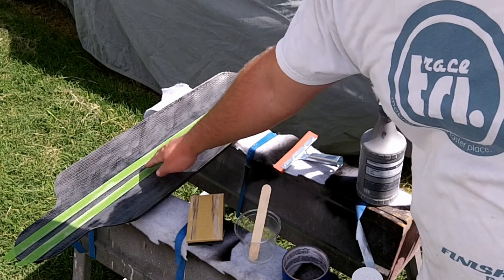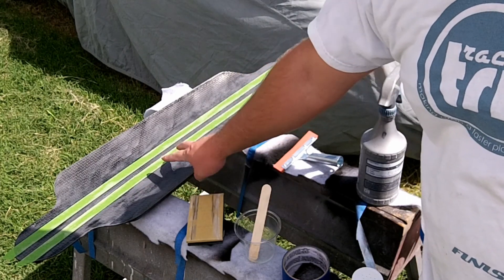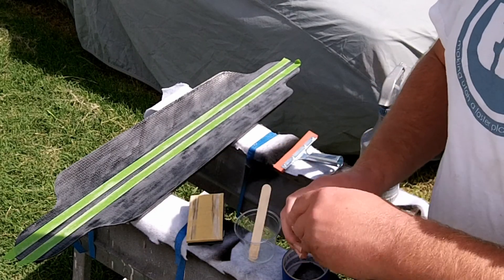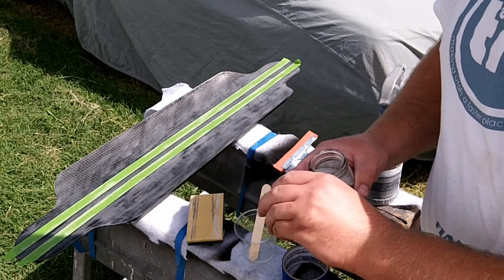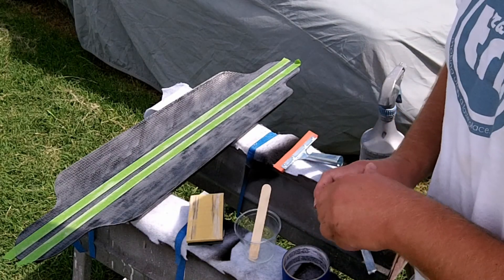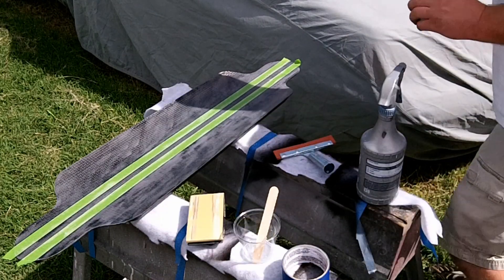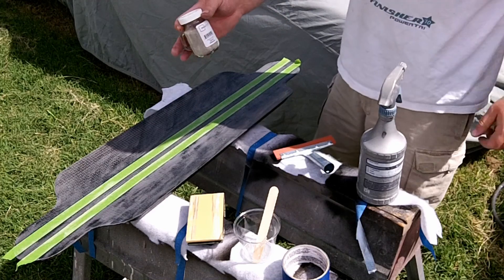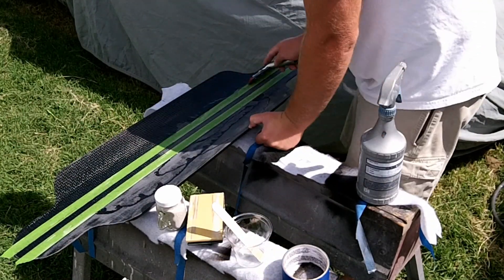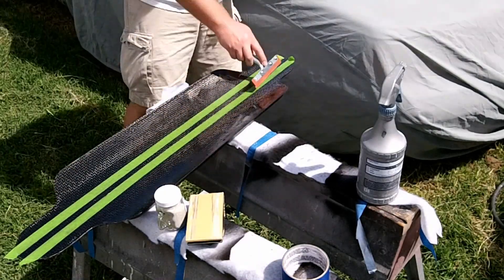You can see here on the board I put some tape down. I still want the carbon fiber to show right there, so I put the tape down and then I sanded this with some 180 or 220 — that's just so the epoxy I'm going to put on there will bond. I've got this TreadX. Instead of using grip tape, I'm going to use some TreadX on this — I didn't want to buy any grip tape and I had this laying around. I think it's going to be cool for the carbon fiber to show through just a little bit on the grip. I've got my epoxy mixed up, I've got my squeegee, and I'm going to wet this out and then sprinkle the TreadX on there. I got this shaker for $0.99 at Walmart.